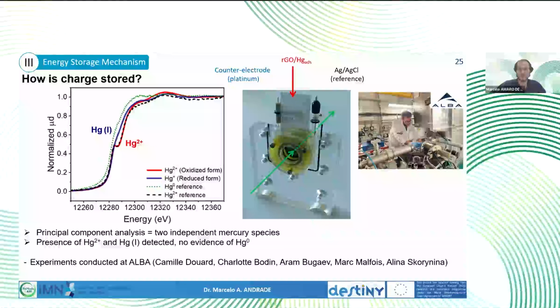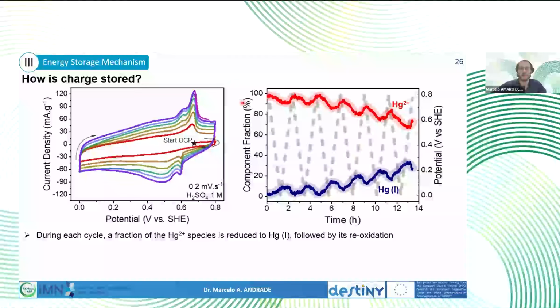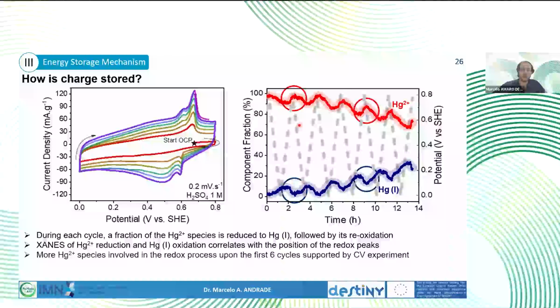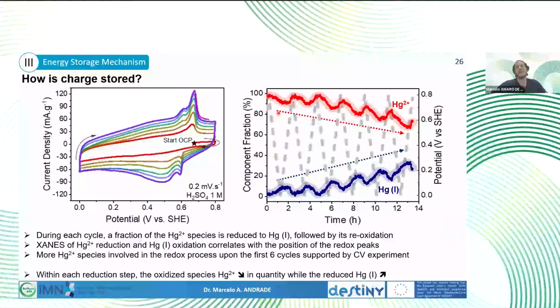So these two species were detected during cycling, and we could see a staircase-shaped response that would correspond precisely to an increase in mercury 2+ when we had an oxidation peak, and a decrease in mercury 1 at the same oxidation peak. So that was very interesting. That was a reversible trend that we could confirm. But not only that, there was an accumulation of mercury 1 and a decrease in mercury 2+. So in the long term, mercury 1 was irreversibly being produced and accumulated in the system.